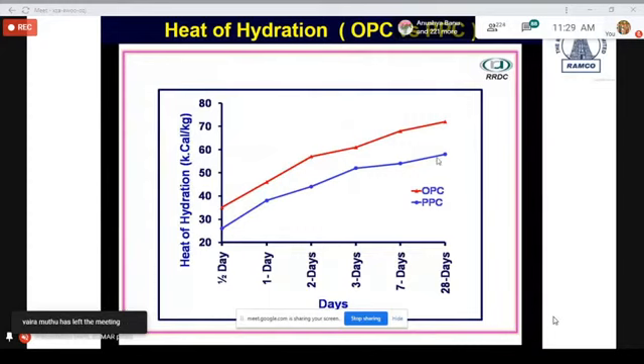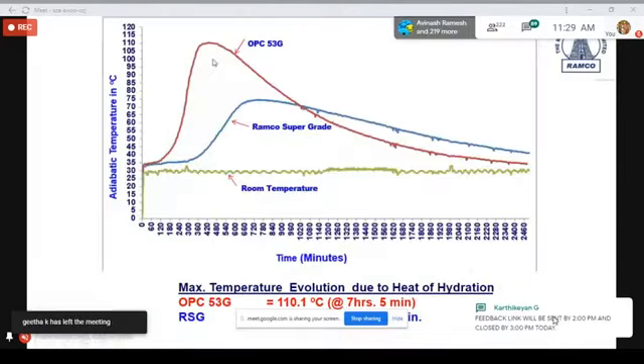Temperature scanners are available, which help you to check the temperature of concrete. This is something very interesting: the maximum temperature evolution taking place in the case of OPC 53 grade and Ramco Super grade, which is a PPC cement. You will find that the maximum temperature evolution is much lesser. So these are some of the tests that can be done to find out how much temperature is there in the case of blended cement or ordinary cement.